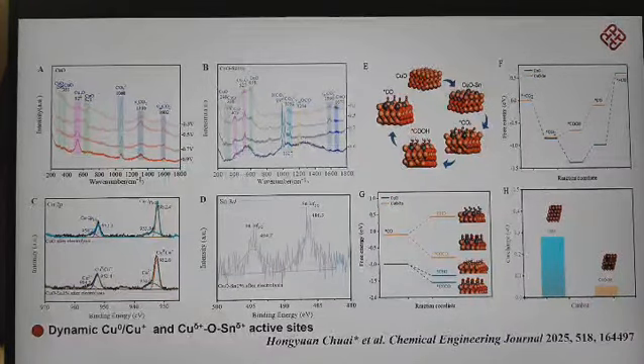To confirm the active sites for C1 and C2 products, we used in situ Raman spectra to analyze the structural evolution and reaction intermediates of copper oxide and tin-modified copper oxide during CO2 electrolysis. As we can see in the figure, both copper oxide and tin-modified copper oxide were reduced to lower valent copper.